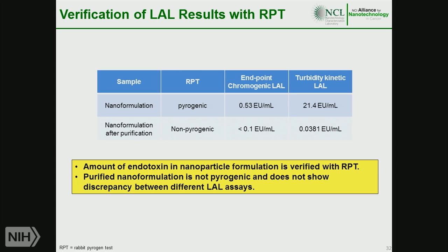Basically, what this test means, you inject material into rabbits and you measure their temperature. And if they develop fever, then it indicates that the material contains endotoxin. The material was pyrogenic, so obviously we confirmed the turbidity data. We sent this material back to the investigator from whom we received it. They conducted purification. We retested the purified material by LAL, and you see that levels of endotoxin substantially decreased.